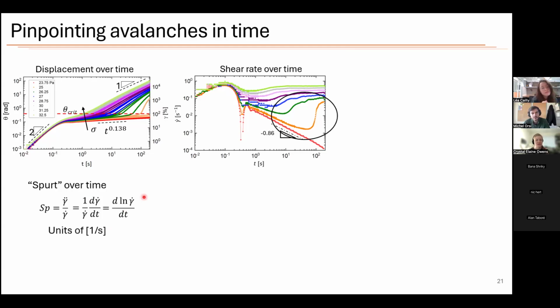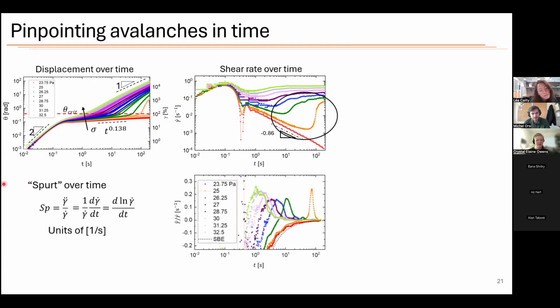And this would have units of rate, given how we've written it. And so if we plot this, what we find out is that it pulls out very clear, distinct peaks for each of these avalanches. And so this is how we've pinpointed them in time. So here we see a relatively indistinct increase where there's definitely something happening. Here we see a clear inflection point. And here we see a very well-defined peak that has a maximum, it has a width, it has a time.